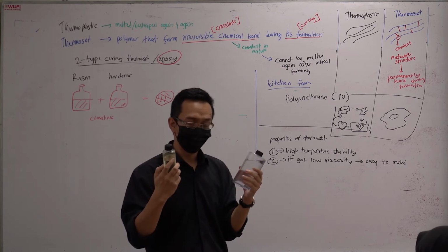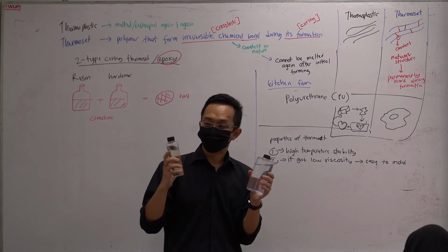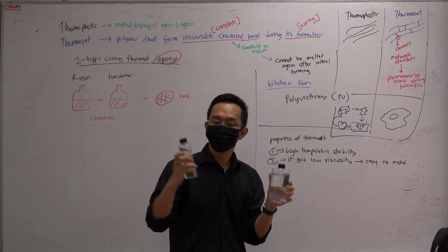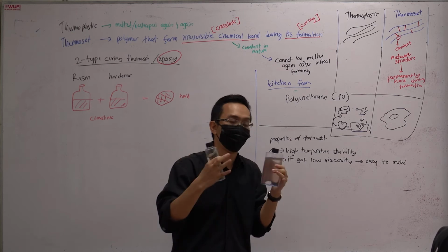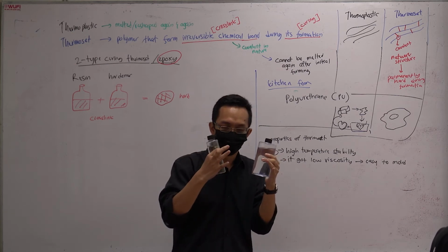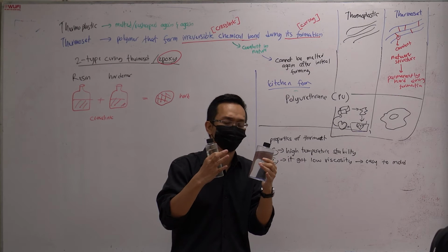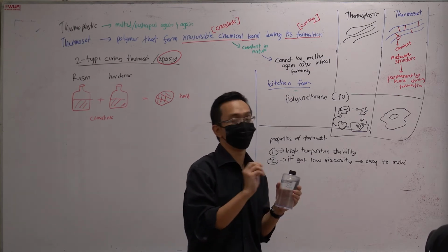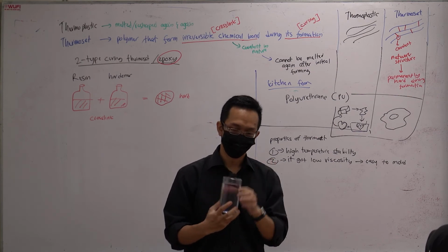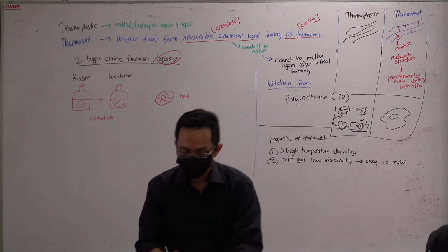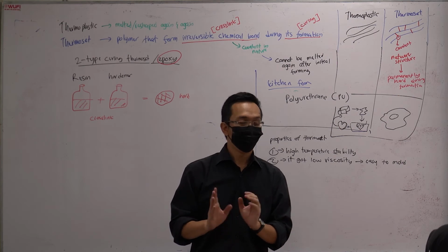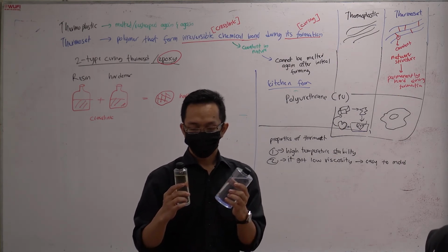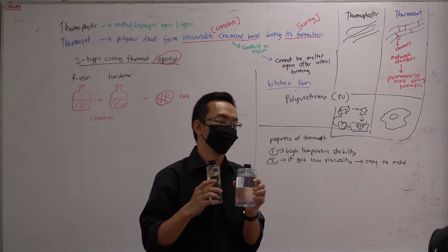So this specific epoxy resin, you need three parts of this and one part of this in order to make a perfect epoxy. Normally you can read it in the manufacturer description. In order to get the ratio, it's not about volume. Normally people don't combine this based on the volume, but based on the weight.